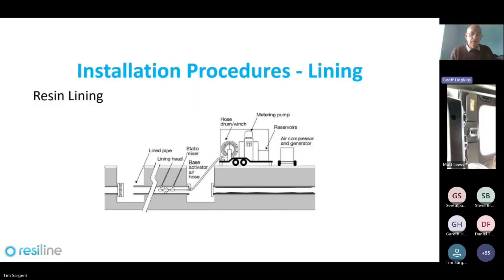basically that umbilical hose, it's got a base pipeline in it, it's got an activator pipeline in it, a compressed air supply line in it to drive your lining head, and it's got some heating hoses. So that's the composition of your hose. As I said, you pull that through to the far end and you will attach a Y block, a static mixer, and the lining head at the far end, because you only want to mix these components right at the very end of the system, really.